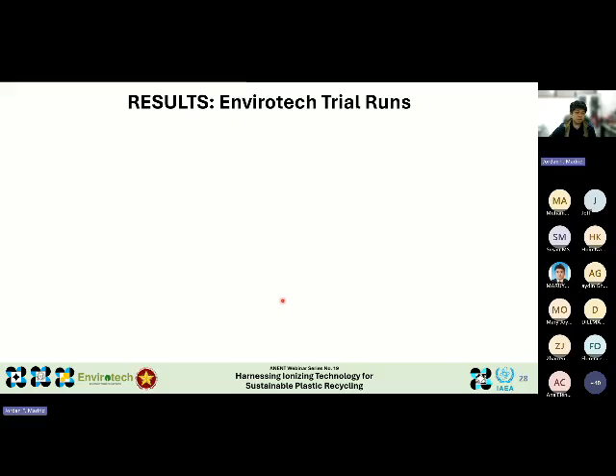Let me move on to the results of our trial runs at Envirotech. I won't go into every detail, but I'd like to highlight some key findings. First, we observed that the optimal blend identified from the large-scale tests was different from the one previously established at the lab scale. The difference was not very large, but it was noticeable. This variation could be due to several factors, among which, for example, the reduced number of processing steps in producing one of the components, particularly the OPP, because in the lab scale we used pelletized polypropylene.